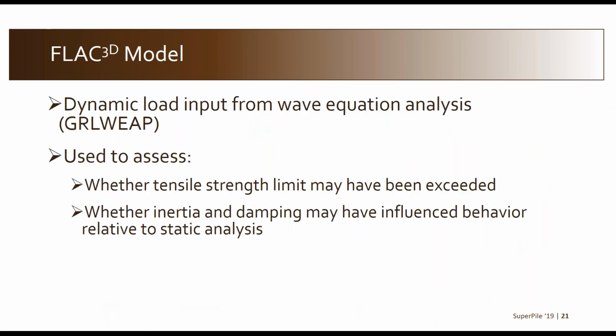We also performed a dynamic analysis of the problem, not necessarily to, quote, see what the answer was, but just to get further insight into, did the dynamics of this come into play significantly? That is, when we consider inertia and damping and the velocity of the wave traveling down the pile as computed from a GRL WEAP analysis, do we expect a vastly different relationship between the magnitude of the compressive stress and then that tensile strain in the hoop direction that we're interested in quantifying? And the answer was no.